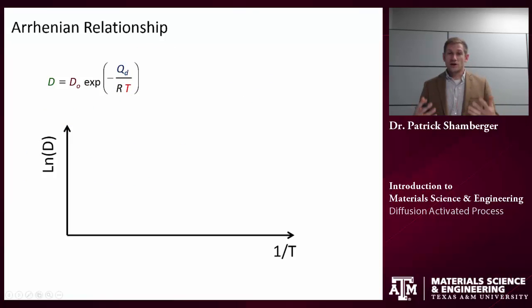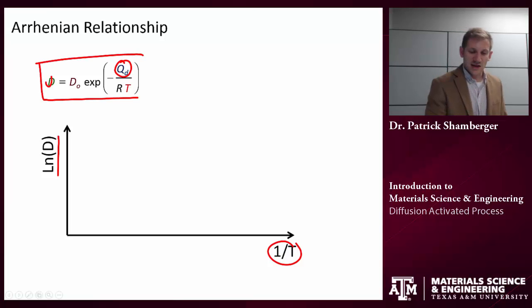When we're looking at activated processes, if we want to measure some data and determine these variables, for example, what is the activation energy for a system, we are going to do that by plotting log of D on the y-axis and 1 over T on the x-axis.